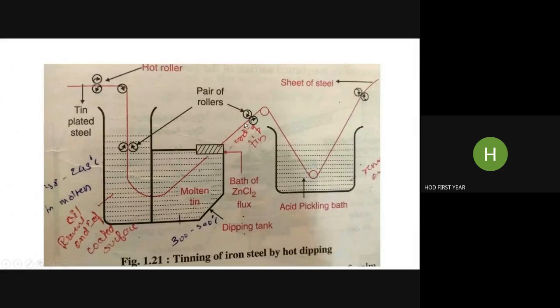So that steel sheet is then passed into the molten tin bath. Here we get coating, but that is not that uniform and adherent. Okay, so it is first passed through the palm oil bath to avoid oxidation, because in hot condition tin gets oxidized, so it is not exposed to air directly. After passing into the molten tin bath, it is not exposed to air. First it is passed into palm oil and then into a pair of rollers in the oil bath itself. The rolling process is done in that oil bath itself.